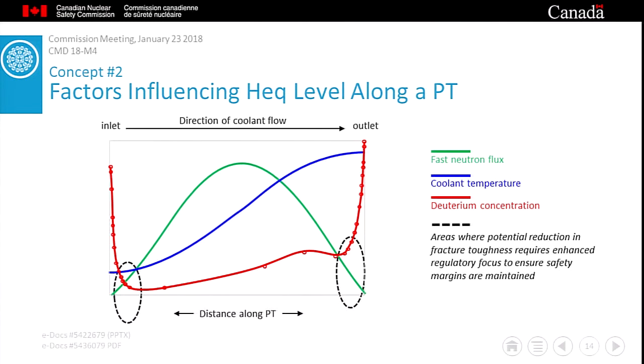Knowledge of this behavior is important for pressure tube assessments. In particular, hydrogen equivalent concentration is a key parameter for establishing the fracture toughness of a pressure tube. Hence, the circled areas at the end of the pressure tube indicate places that require enhanced regulatory focus because of reduced fracture toughness. And I'll be giving you much more detail on that in a couple of slides.